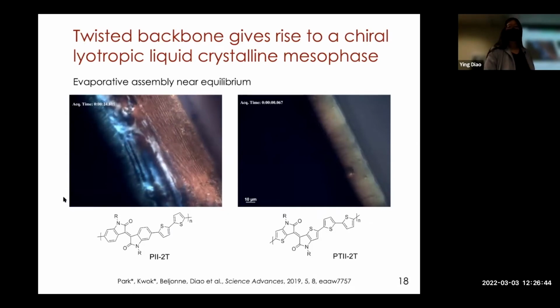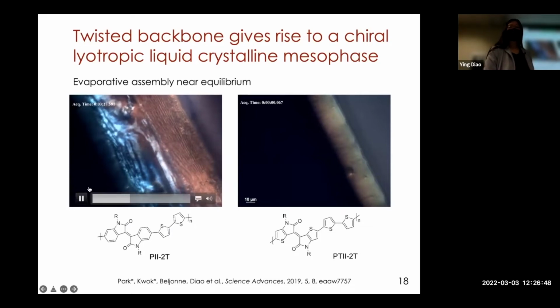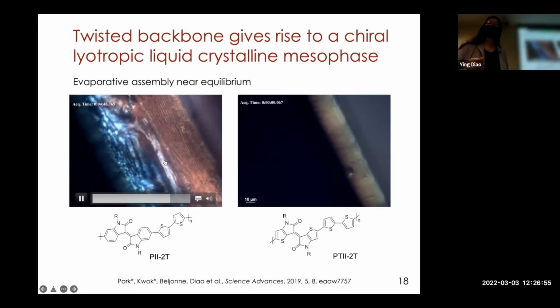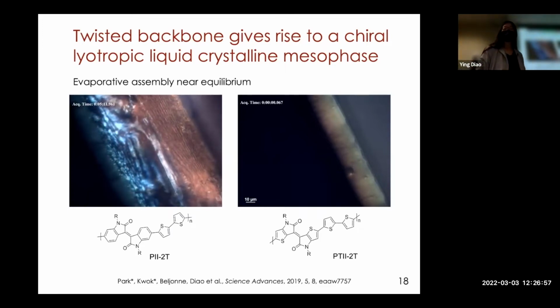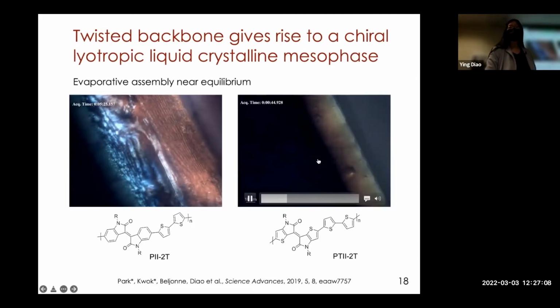So for the twisted polymer, we saw that if we print slowly, before the ink dries into a polymer thin film, we observe a blue phase, which is a chiral crystal mesophase. That is very surprising to us because the polymer itself is achiral. Whereas when we print the planar polymer, we bypass the mesophase altogether.